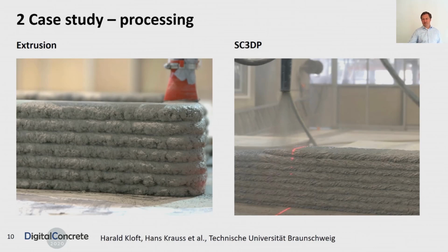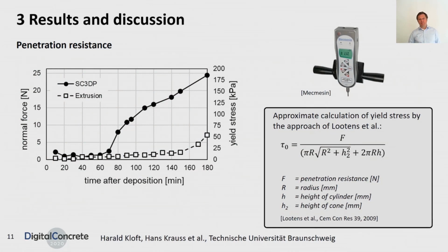On the left side, you can see that it may not be perfectly optimized for the purpose of extrusion, but however, in the inside, in the middle of the strands, we have a rather homogeneous microstructure, and there we took the prisms from. Now let me first come to results in the fresh state.